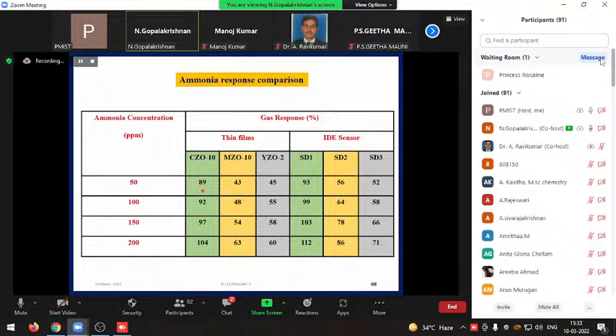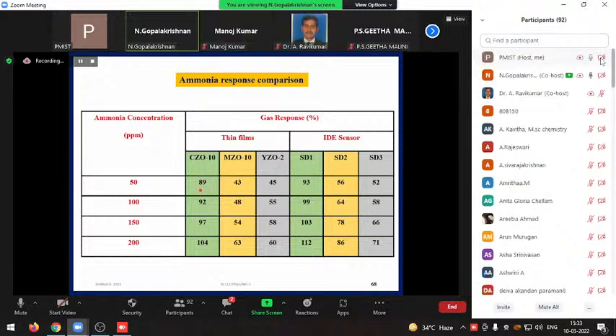You can compare, you can see here, the first case. So here, for the ammonia sensing at 50 ppm concentration, the thin film gas sensor responds only 89. Here we got 93. Here 92, we got 99. 97, 103, 104, 112. That means the IDE response is much higher. Again, with this Mg, here 43, 56, 48, 63, 86. Again the yttrium, see here. If you compare, all these values are higher than those of the thin film sensor. That is what I want to emphasize: the IDE sensor is more efficient than the thin film sensor.